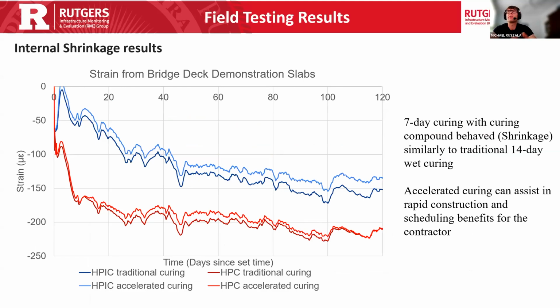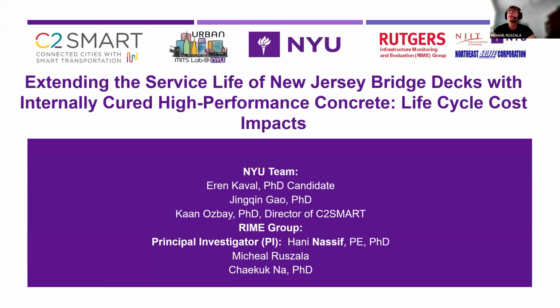And going into the comparisons between 7-day curing, 7-day curing with curing compound, and the 14-day wet curing, we see that for both the HPIC and the HPC, these materials behave fairly similar. So it is something to look into as a possibility for accelerated construction, especially if you're getting the benefit of the significant reduction in strain for the HPIC.